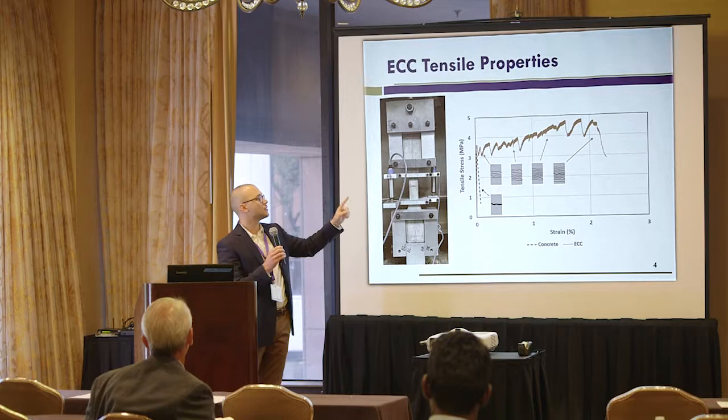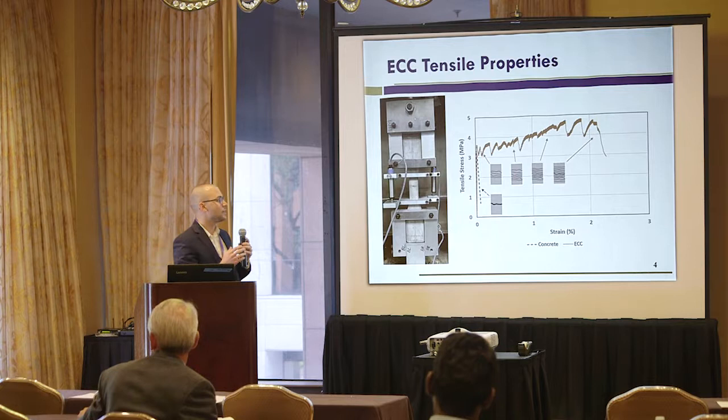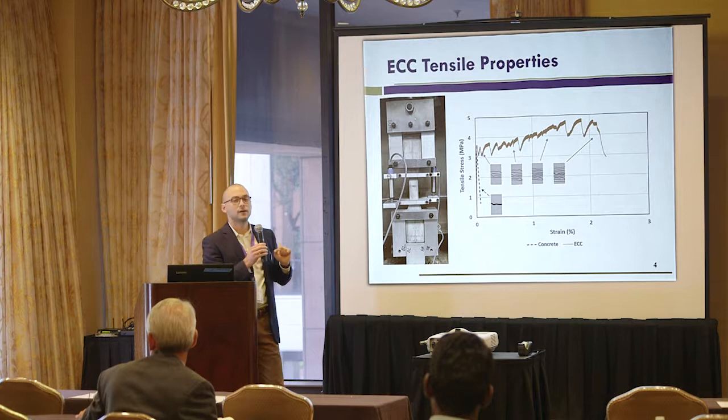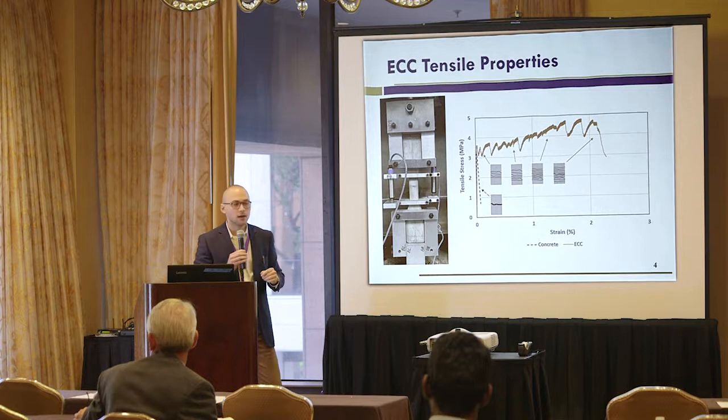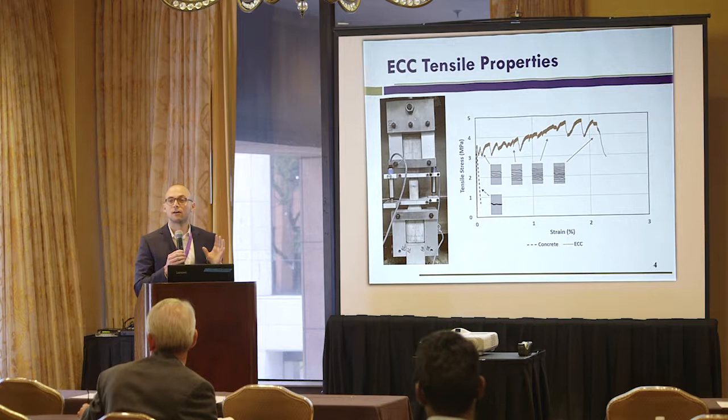With further strain and deformation, you have an increasing load carrying capacity. That is a process that takes place with the formation of multiple cracks, as you can see in this figure — a bunch of multiple cracks — until final failure, where one single crack opens and you have a complete collapse of your material. The ductility of ECC compared to traditional concrete is around 100 to 500 times more deformation capacity, which is huge.